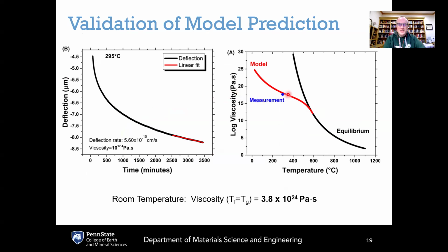Oscar did some fairly heroic viscosity measurements here. He actually measured a viscosity close to 10 to the 17 Pascal seconds, a direct measurement of viscosity, which took him weeks to do because of how slow the flow was. And the model predictions here are shown in red and in black.